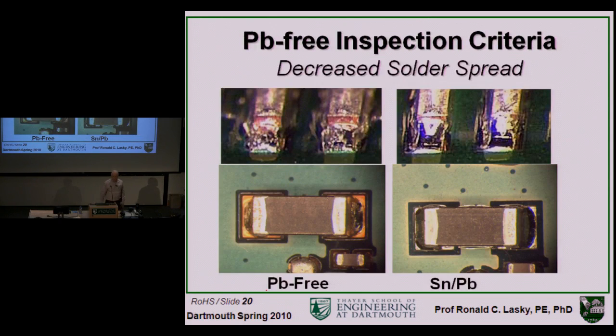So one of the issues, this shows a pretty good example of it not wetting well. This is a top view of what's called, again, a passive component, a capacitor or resistor. This dimension here is probably, this looks like a little bigger one, 80 thousandths of an inch. So this is tin lead solder. And you're looking down, and you see the solder joint is here, and you see the solder is spread out on the pad completely. You can't see any copper color. But here, you can see the copper of the pad. It didn't completely come out and wet the pad. So that's a common thing with lead-free solder.